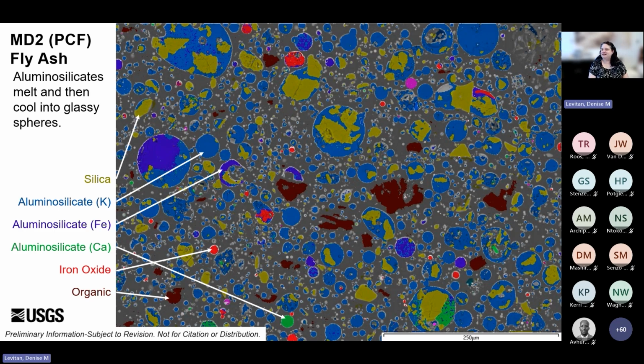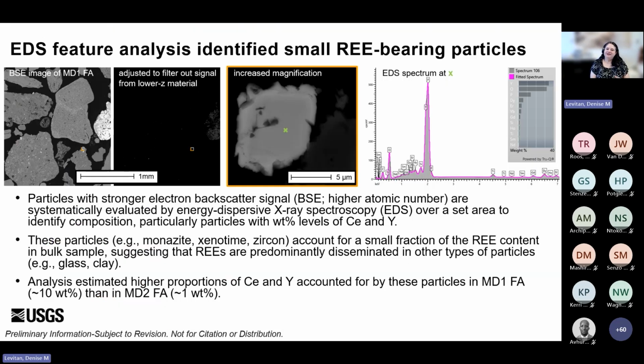The rare earth elements tend to be trapped within these glasses, and it takes a lot of acids, or strong bases then strong acids, to break these solids down and get the rare earths out into a solution from which they can then be separated by, like, solvent extraction or ion exchange. And so it's an intense and therefore expensive processing. So finding ways around that would be presumably less expensive and easier. So like I said, how to extract them does depend on what minerals are present in the CCR, and then what minerals the rare earth elements are contained within.